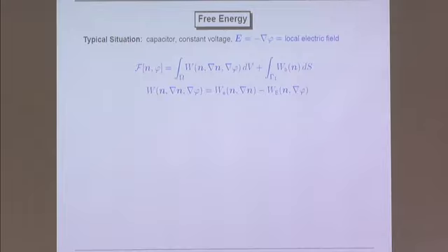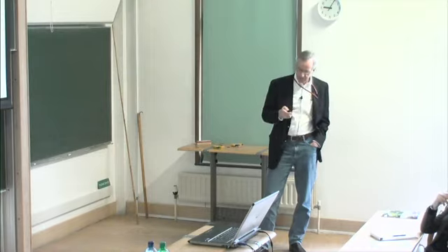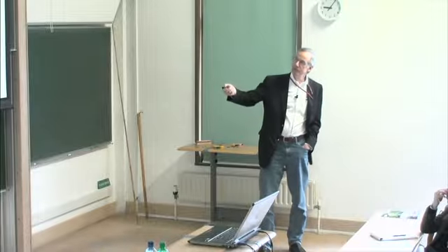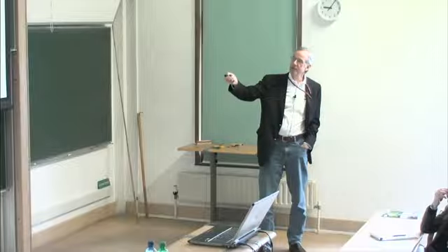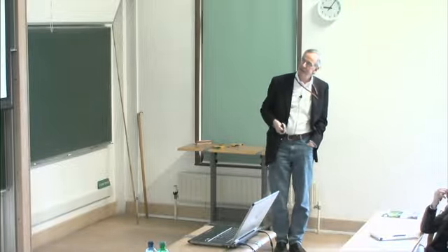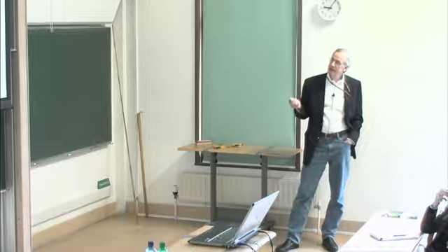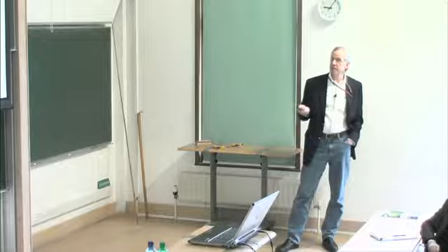some generality. And now the free energy density here has a distortional part, kind of a typical Oseen-Frank part, and then the piece related to the coupling to the electric field. The distortional elasticity is just Oseen-Frank. The simplest thing you can think of would be an equal constant version of that model, which is adequate for what I'm worrying about here. N is the director field, forced to be of unit length throughout the entire region.